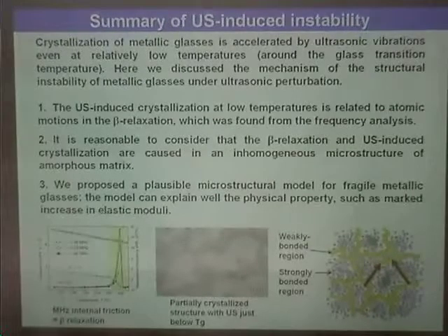No, you can reconstruct from the width of the first peak of the PDF, which agrees with the model. And the model says that the density fluctuation is 6%. 6%. So that's 6% between the densest region and the least dense region? No, it's sigma squared. It's a Gaussian distribution. The distribution of densities has a width of 6%. Yeah. That's for a very soft potential, right? 12%. That's much softer than the Lennard-Jones potential. That's correct. Yeah. But this is from simulations, you said.